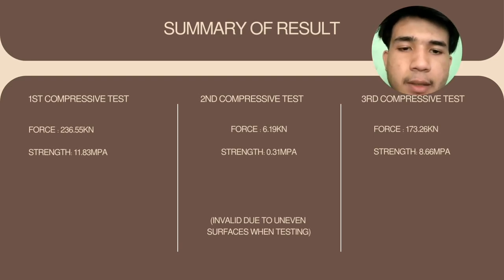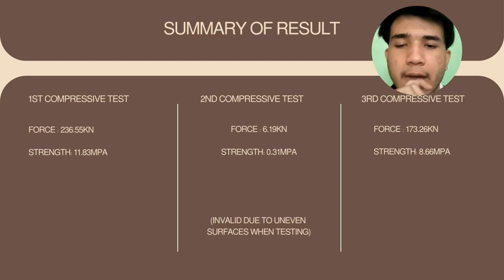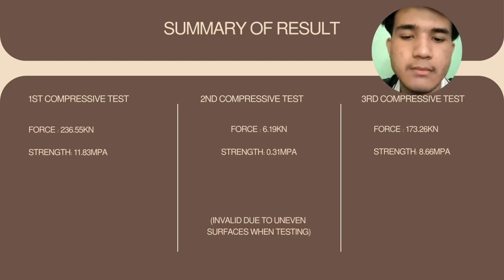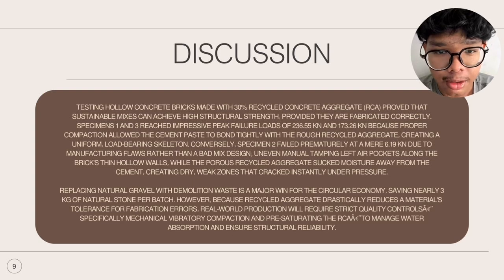before it fails. So for our third compressive strength test, the maximum force is 173.26 kN and the compressive strength is 8.66 MPa, which is valid. So the discussion from our slide is: testing hollow concrete bricks were made with 30% recycled concrete aggregate to prove that sustainable mixes can achieve high structural strengths provided they are fabricated correctly.